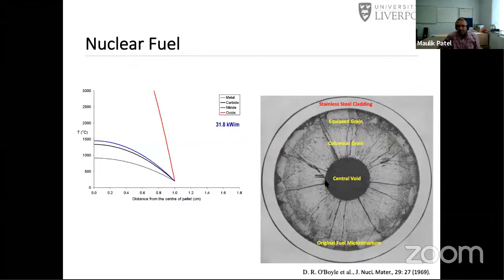And so as the temperature rises, you have migration of pores, you have migration of oxygen, you have migration of these cracks, and those migrations lead to these changes in the microstructure. At the beginning of the fuel pellet, the microstructure, which is the grain, looks like this, where my pointer is, if you can see that. But when you have a temperature gradient, your grain structure changes, it becomes more columnar, and as your grain structure changes, your thermal conductivity changes, and so your reactivity changes basically. So this is a microstructural migration when you have a temperature gradient in a fuel pellet.